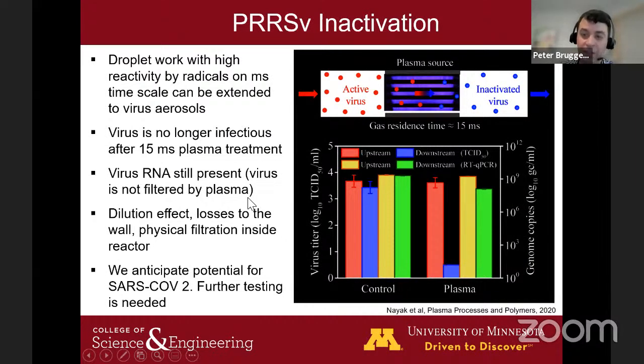However, just as I said, the plasma in this case is not a filter, okay? And this is kind of interesting, and we understand now why, because we are oxidizing the capsid, certainly in these, it's soft treatment, but I mean, it's not over treatment where you destroy everything. You see that actually when you look to the RNA in this case, a lot of the virus particles are still there, but they are no longer infectious. So it's a quite different mechanism than you would expect for filters.